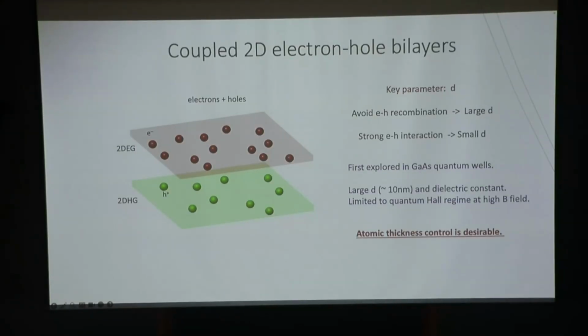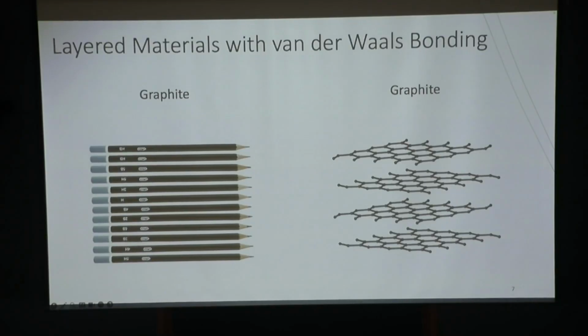And to address this challenge, we'll make use of this now emerging material family known as van der Waals heterostructures, or basically layered materials with van der Waals bonding. Everyone is familiar with writing with a pencil. So that's one of the most important layered materials, which is basically graphite. When you write on your paper, you are exfoliating thin layers of graphite because they have very strong in-plane covalent bonds, but very weak interlayer van der Waals bonding. So as a result, you can exfoliate these layers very easily, even when you are writing with a pencil.